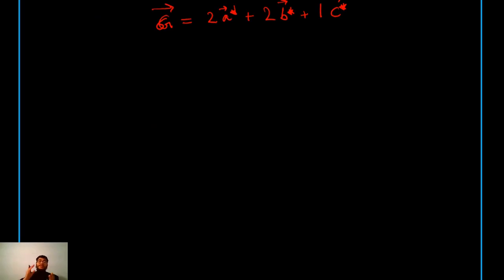As we can see, there is a relation between Bragg's law, which deals with the interplanar spacing, and deals with not lattices but basically planes. That has a connection with a g vector which is indeed perpendicular to those planes. So that kind of gives us some hint that the Laue condition and Bragg's law might be having some commonalities.